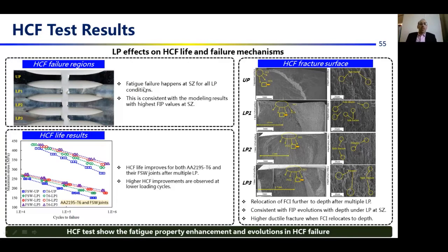The high cycle fatigue test shows the fatigue failure happening at SZ for all laser peening conditions, which validates the modeling results. And HCF improvement can be observed for both aluminum lithium alloy and these FSW joints, and it's more noticeable in the lower applied cyclic stress, which shows that laser peening has higher effect in the high cycle fatigue than the low cycle fatigue regime.